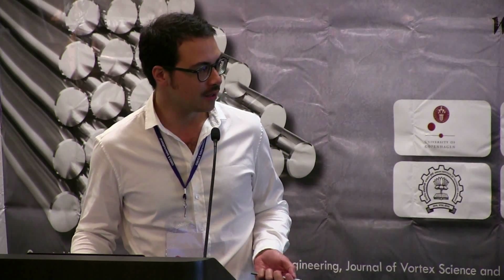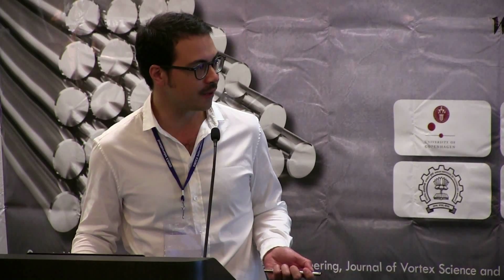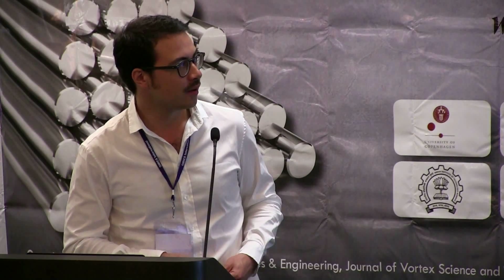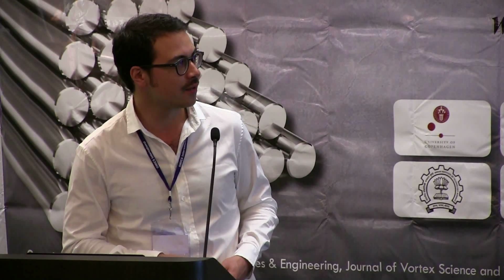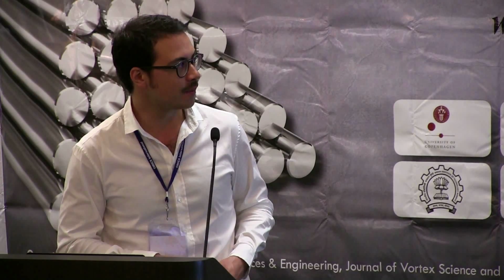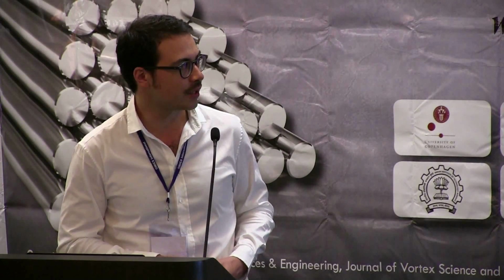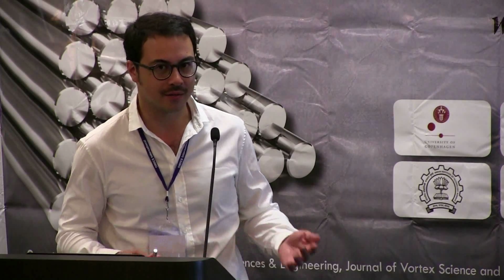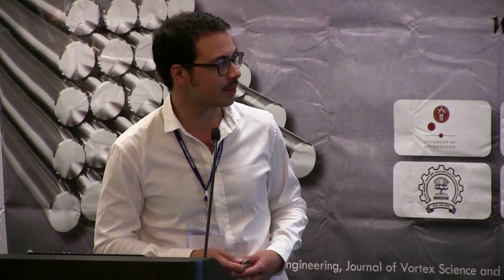So the SMA training is for minimizing running-in effects of SMA devices. And for that we have a kind of test rig. The requirements were that we have wire diameters from 0.3 to 0.8 millimeters that can be trained with this machine, and heating temperature up to 400 degrees Celsius, and the design for stress was up to 400 Newton per millimeter squared, regarding 0.8 millimeter wire diameters.